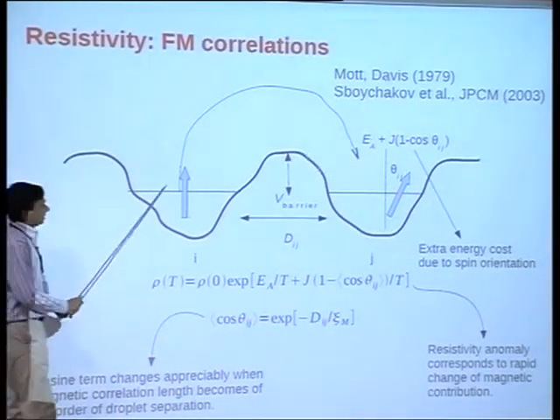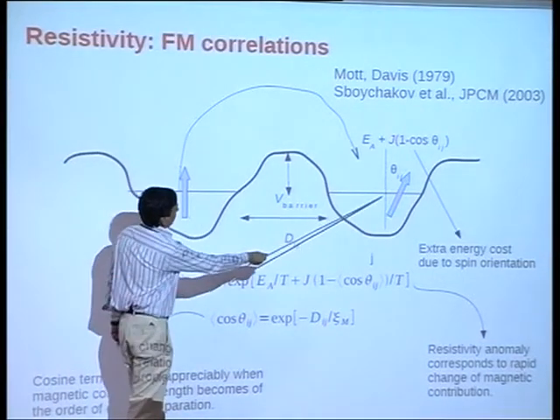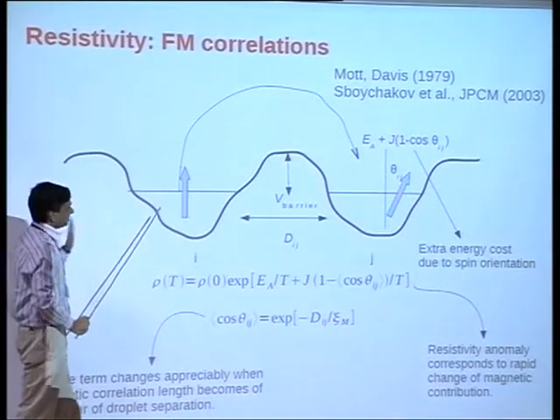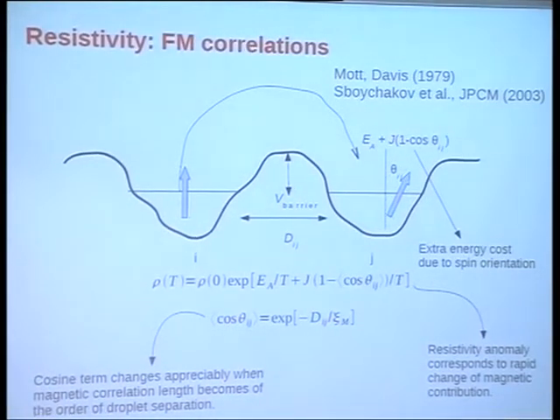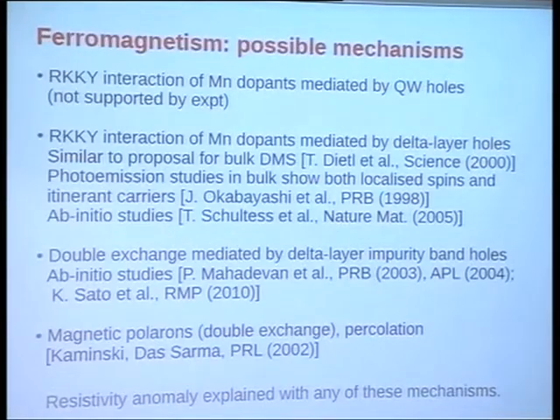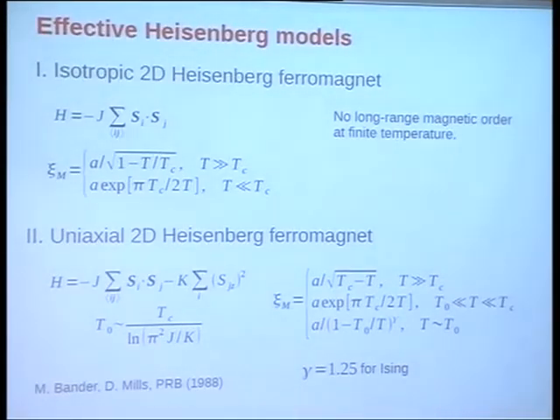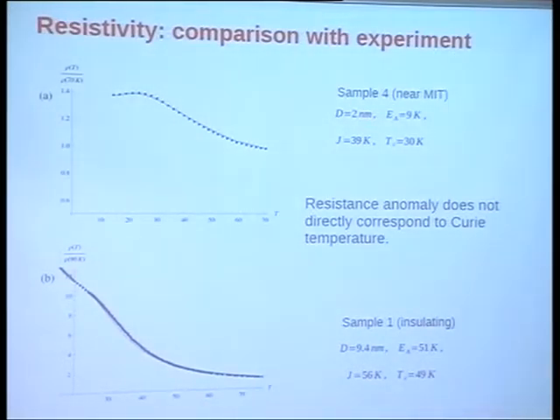Whenever this magnetic correlation length in the Mn layer becomes comparable to the interdroplet distance, you have a much easier hopping of charges and much less scattering. After that, you can go on increasing your magnetic correlation length, but it has relatively less effect on the transport. So the anomaly of resistance doesn't tell you about Tc. It depends on Tc, but doesn't give you a measure of Tc, and it will in general in these 2D systems lie below the actual Curie temperature. This is different from 3D because in 3D the correlation length will diverge at the Curie temperature, and so you should have the resistivity anomaly pretty close and a bit above Tc.